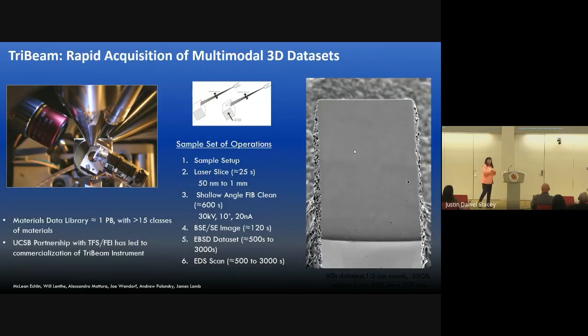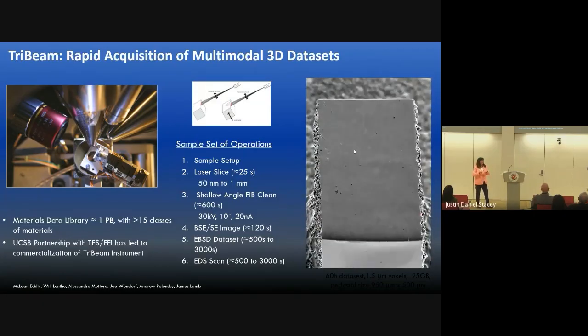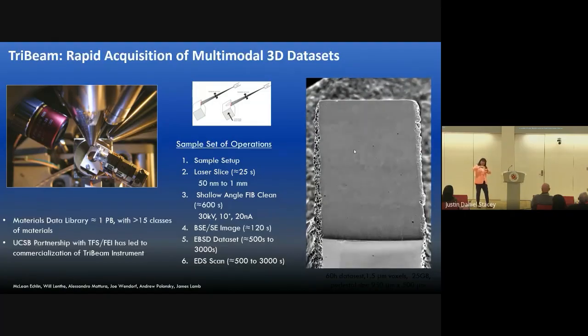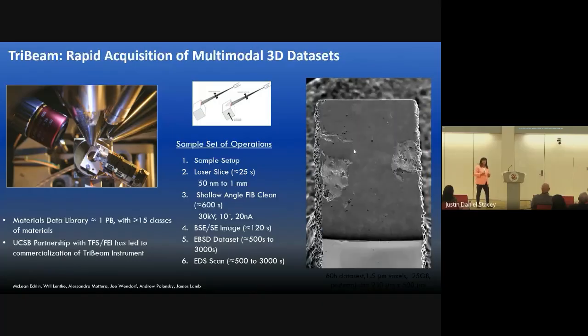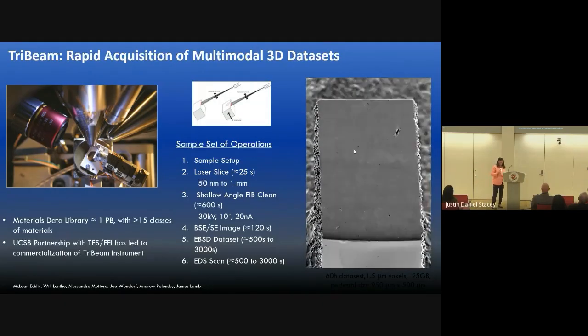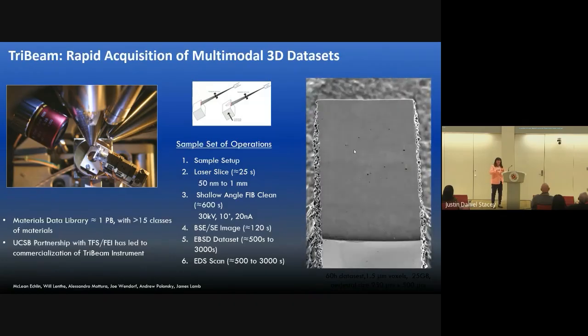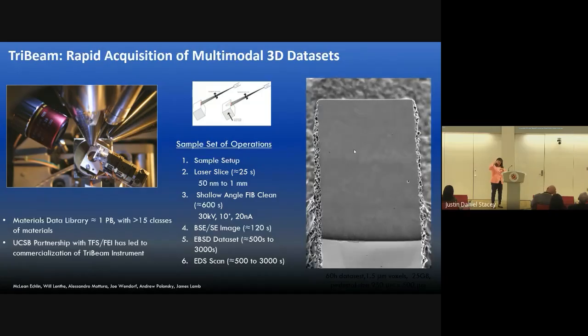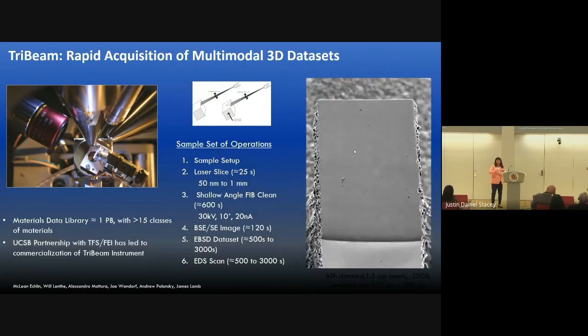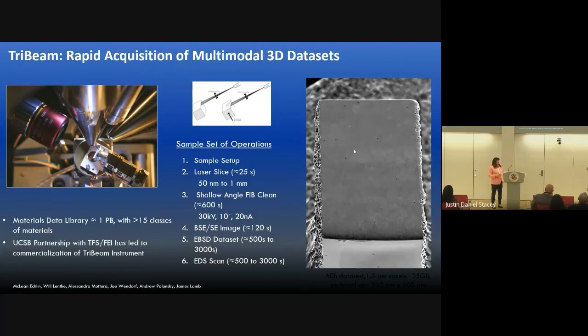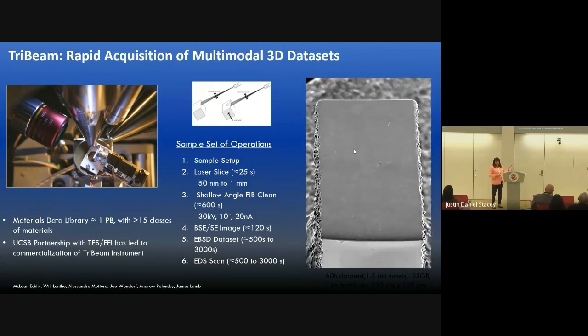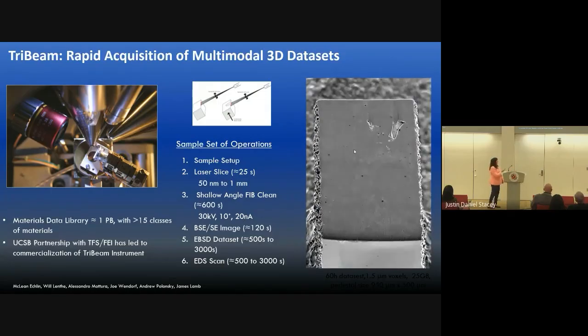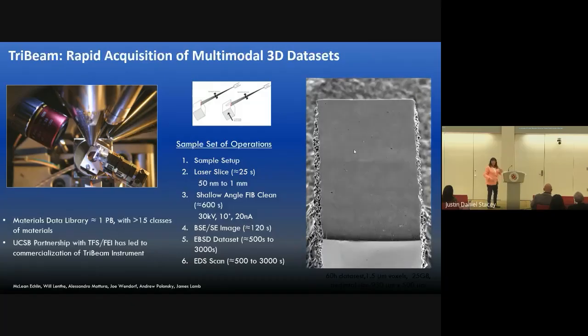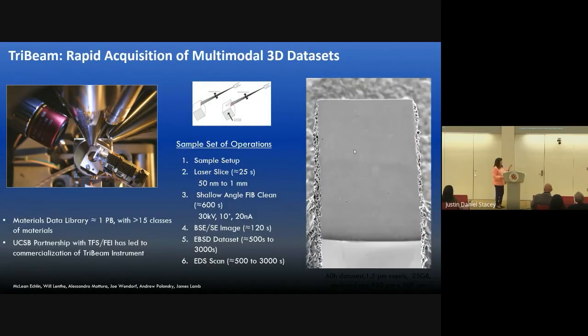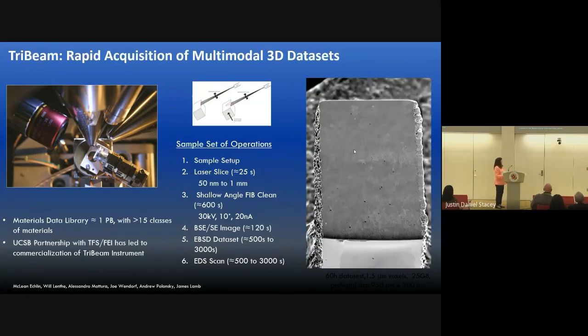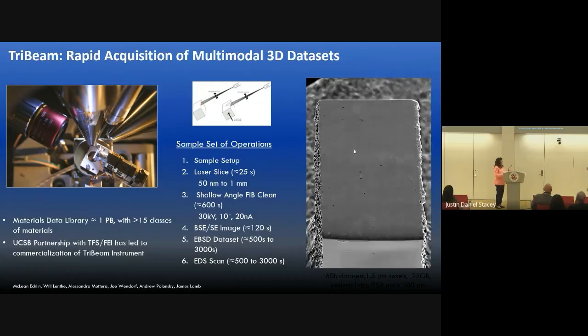So why femtosecond? You ablate material, picoseconds, radiation is constant. And so if you have a pulse that's longer than that, as you ablate material, it wants to pump energy back into the ablated material and then deposit it. That would be melted. When you have femtosecond pulses, the laser's off, the material leaves, and so you get these very high quality surfaces after the ablation, which you can image by backscattered detectors or EBSD, and so you have a way of getting this multimodal data as you tilt around in the microscope.